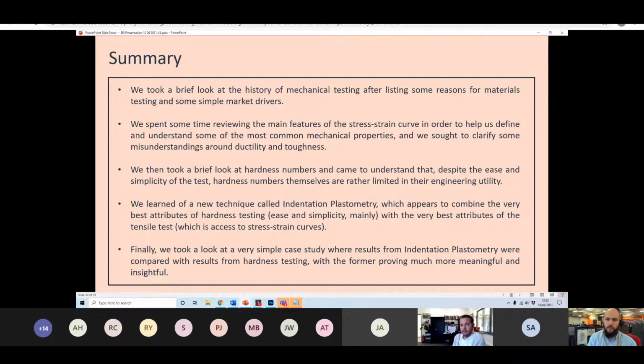Okay, and related to that question, I've got a question for myself: for smaller components that would fit in the testing volume, can it be used as a quality assurance method at the end of a production line, for example, to ensure that you have got the parameters you expect after, say, welding or additive manufacturing, where you've got the layer heights and things like that as well? Yeah. So you absolutely could put this at the end of a production line or somewhere in the middle of a production line and do some quality assurance testing in the same way you might do with a normal hardness test. Again, we would say that you get more meaningful information from indentation plastometry because you get stress strain curves. And as we highlighted, suppose you're on a production line, it's going through a furnace or something, there's a heat treatment taking place. What happens if that temperature is out for some reason? You get a slightly different stress strain behavior in the material because it's been annealed slightly differently maybe.